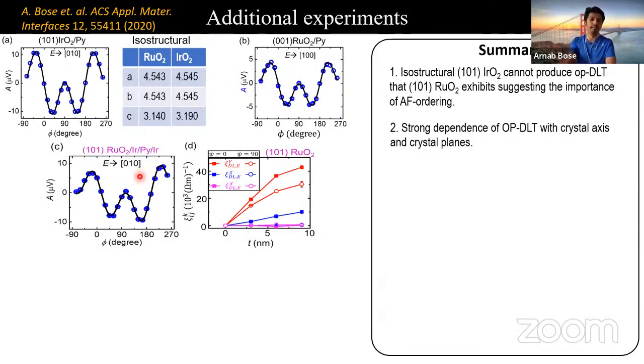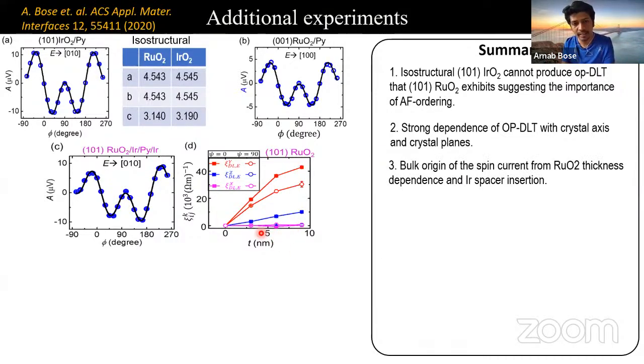We have also studied the torques by having a spacer between ruthenium dioxide and permalloy. We see the signal strength goes down, but we can still measure a detectable extraordinary torque, meaning the spin current is generated from the bulk bands, from the bulk of the ruthenium dioxide. And we also vary the thickness of ruthenium dioxide, and we find the spin torque efficiency increases and tends to saturate when the thickness is about 10 nanometers. So this is all consistent with the theoretical predictions.